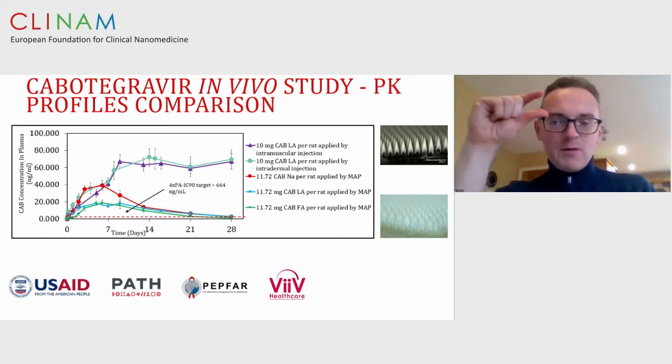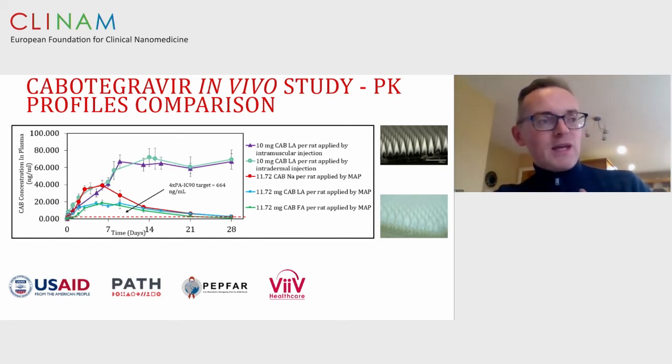Some of the drug is remaining above the stratum corneum, as evidenced by a sort of white residue on the surface of the skin. We were estimating that the efficiency of delivery with the microneedles in this case was about 15 to 20% of the drug loading. So a lot of our subsequent work, and our work at the moment, has been on improving the actual delivery efficiency. Again, the patch size for 7 days would be somewhere between 20 and 30 square centimeters.